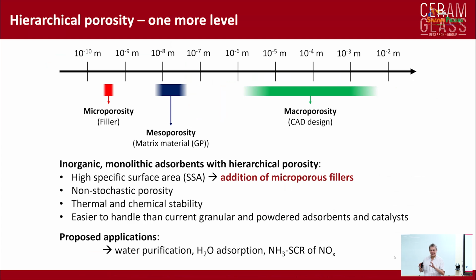Okay, I didn't mention one thing. Here you certainly want to have also a decent mesoporosity. So what we did was that we started using clay, for instance, bentonite, as a rheological modifier for the geopolymer. So we got rid of the PG, which blocks the mesopores, and now we use a certain amount, I think 10 to 20% of clay, which provides a very suitable way of controlling the rheology. And clay does not bother us because we are using the components at room temperature. They are not fired, so there's no decomposition of the clay.